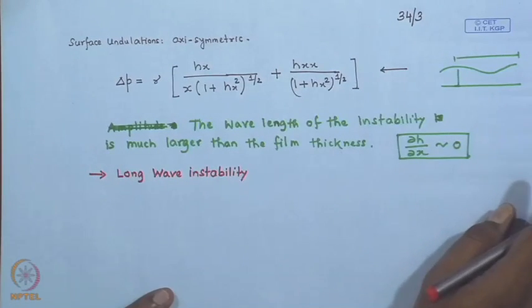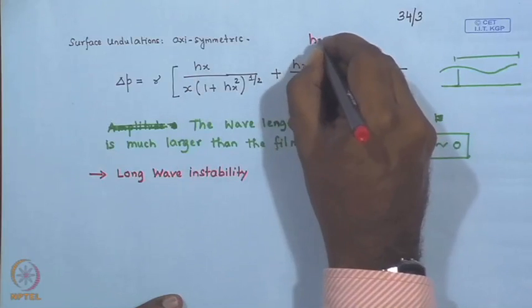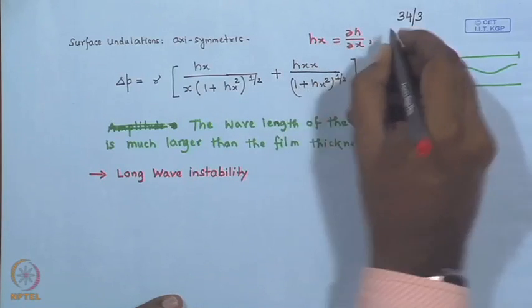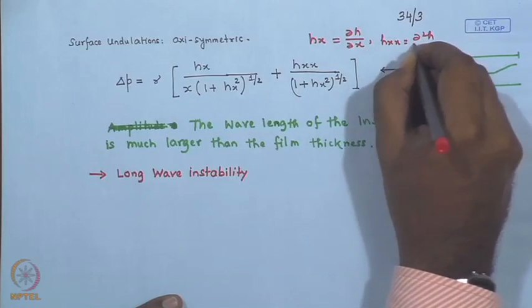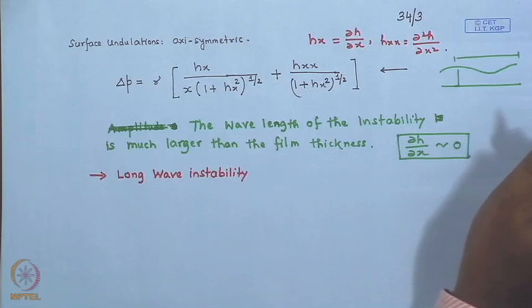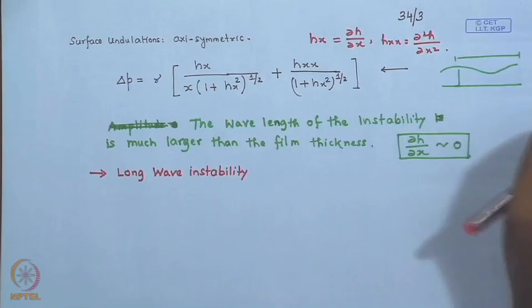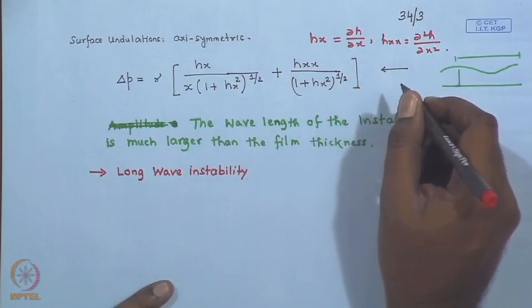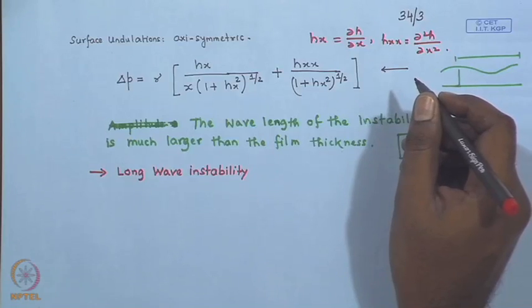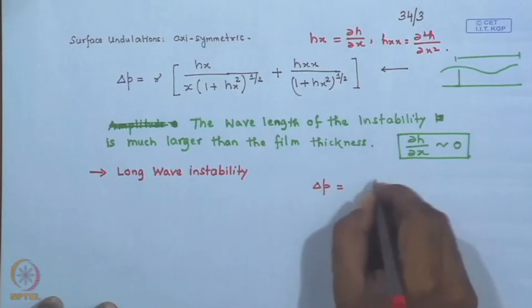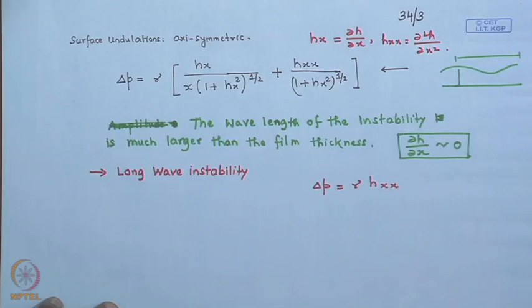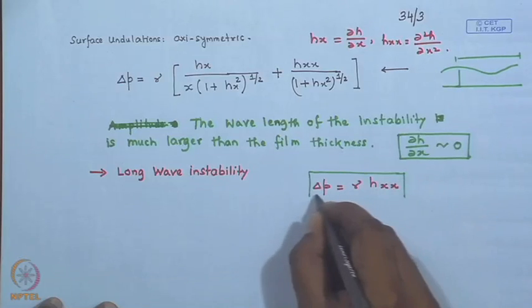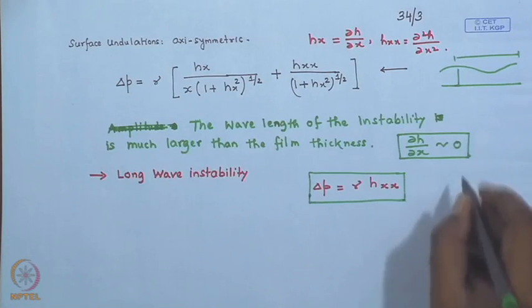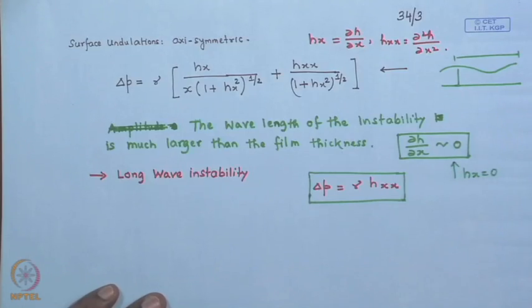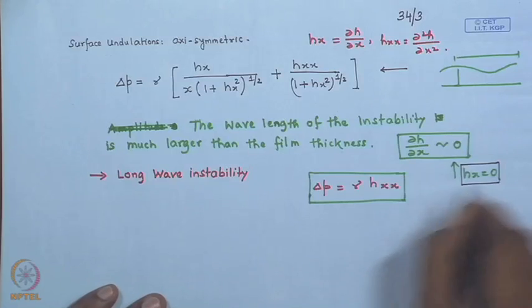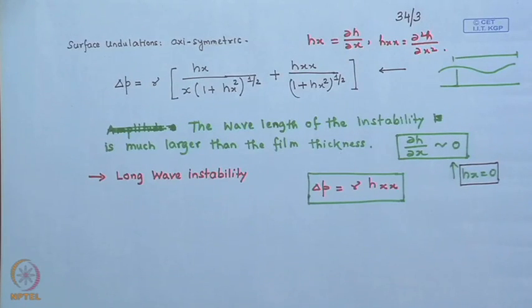So, if you now plug in the condition of long wave instability, let me just remind you, H x in this equation implies del H del x, H x x refers to del 2 H del x square and so on. So, if we now plug in the condition of long wave instability into the expression for Young-Laplace equation for an axisymmetric surface, we get a very neat expression, which is delta p equal to gamma times H x x. Now, please do not confuse yourself with the fact that if H x is equal to 0, H x x also has to be 0. You just refer to your basic fundamentals about optimization or maximum minimum.